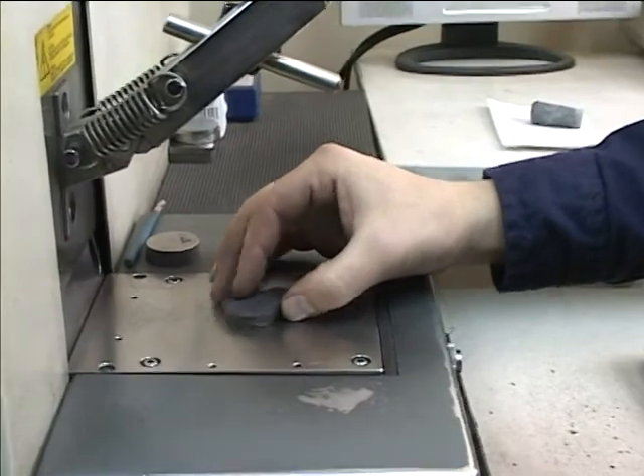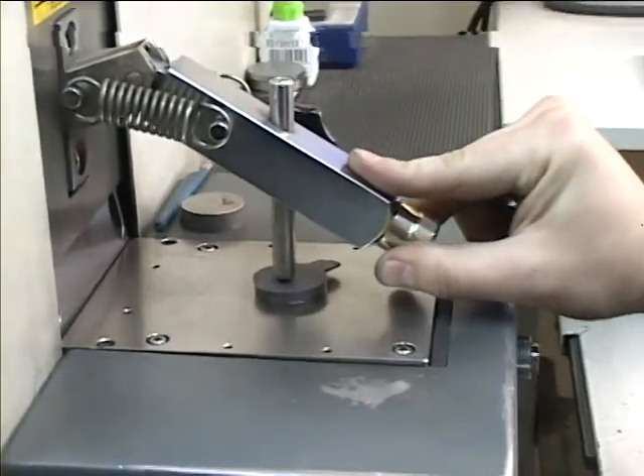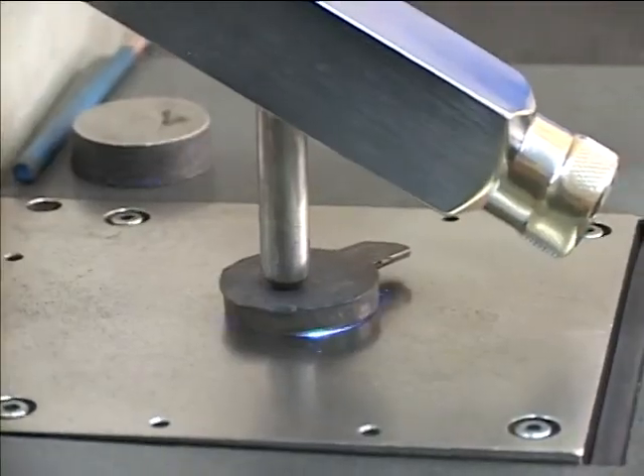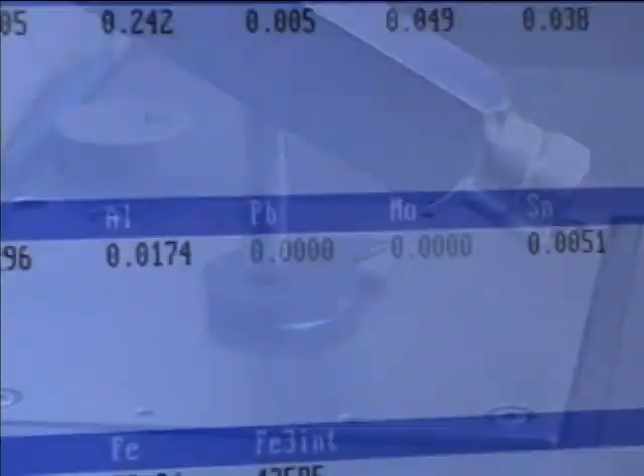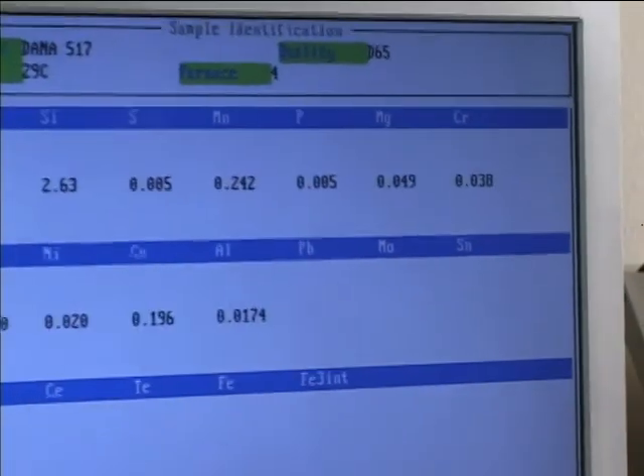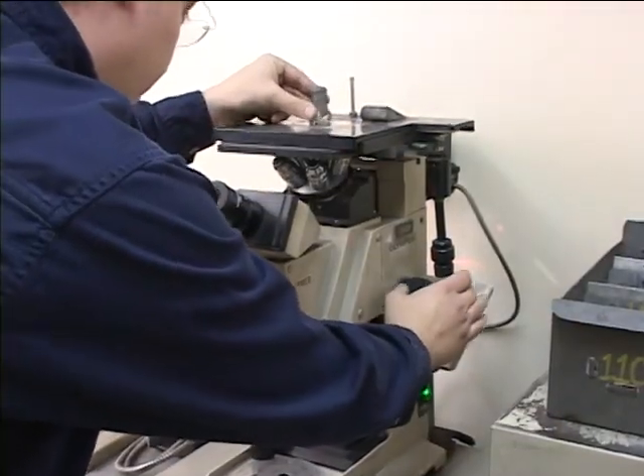Just like with other casting methods, we test everything to ASTM standards. From a mechanical stress standpoint, lost foam ductile iron is no different from green sand ductile iron. And from a microstructure standpoint, it's actually better because there's no chilling effect on the metal due to the fact we use dry, unbonded sand.